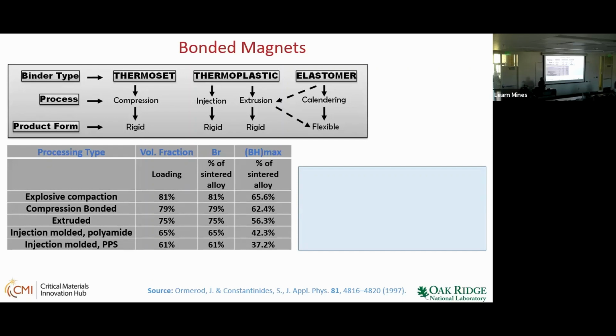So each method may dictate how much loading you can do, because already June talked about if you reduce the dysprosium, you're going to need to add more, and the magnetization, all those things may really go down. The thing people always get confused about is that volume fraction is related to the remanence and the energy product. So BH max, we know. So the compaction, compression bonded, extrusion, injection, and all those things. Every polymer, based on its viscosity, because some polymers may be highly viscous, then you cannot load more magnet powder into the polymer. The higher the viscosity, the less. So if you go to PPS, polyphenylene sulfide, 61% is what you can do. Or with polyamide nylon, you can do 65, and the energy product will go down.